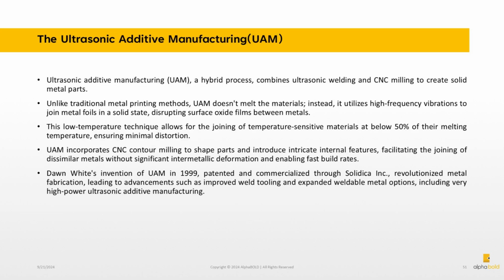Ultrasonic additive manufacturing, UAM, a hybrid process, combines ultrasonic welding and CNC milling to create solid metal parts. Unlike traditional metal printing methods, UAM doesn't melt the materials. Instead, it utilizes high-frequency vibrations to join metal foils in a solid state, disrupting surface oxide films between metals. This low-temperature technique allows for the joining of temperature-sensitive materials at below 50% of their melting temperature, ensuring minimal distortion.